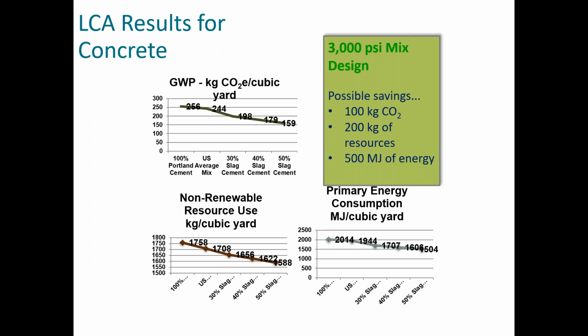One of the things that we do see is that using slag gives us a lot of synergies when we're using it with PLC, or even when we're using it with ordinary Portland cement. We're seeing a lot of benefits, not only from the energy side, but also from the durability aspects, the workability aspects, the color reflectivity aspects of slag cement, and a bunch of other reasons for using slag. When we look at the global warming potential, depending on the cement we're using, if we're using 100% cement, we see the global warming potential is going to be a lot higher than as we reduce it by using slag.